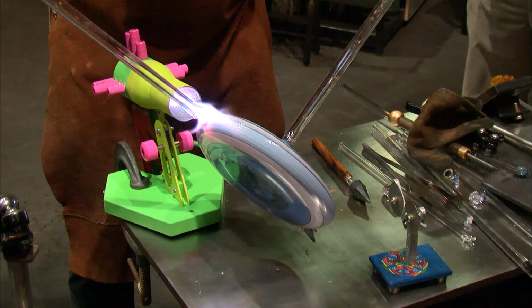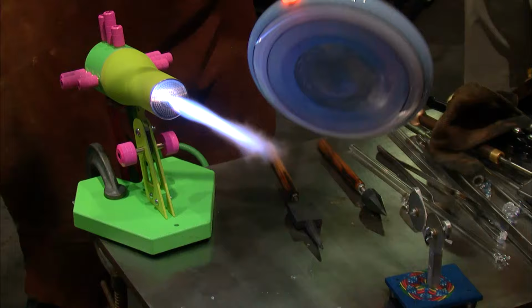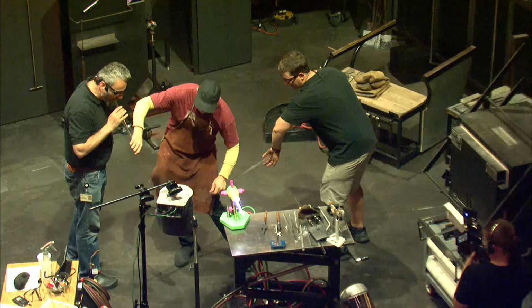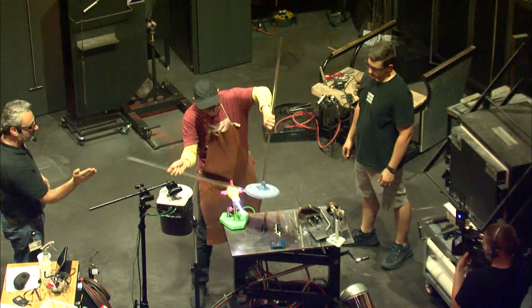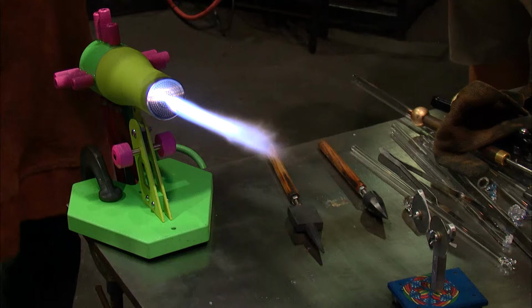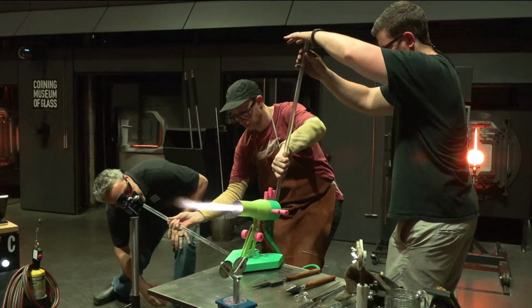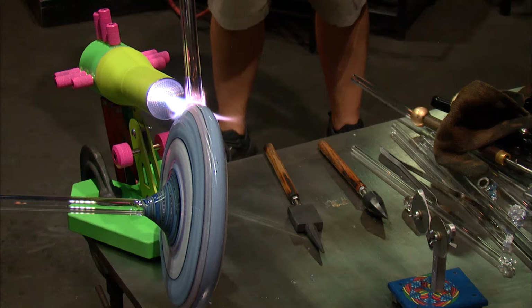So getting the temperatures set up just right, getting these aligned just right. With borosilicate, getting those temperatures really precise for attachments is crucial. All right. So, you're tilted. Oh, I am tilted. Yep. There you go. So, as you heat the ends of those openings, they get a little thicker. So as he makes the attachment, right where that seam is is a little bit thicker than the other bits of wall thickness there. So heating and then puffing a little bit to make that seal more uniform.